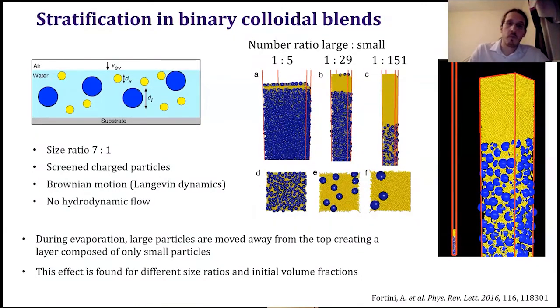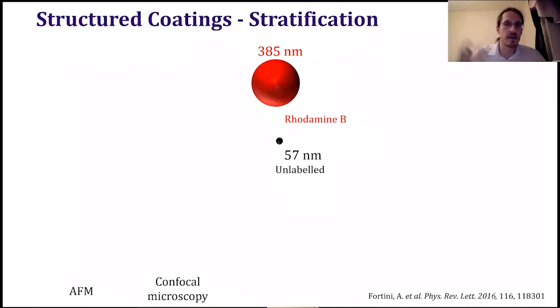So what I did here was check experimentally that this process happened. I blended particles, where the large particles have a red fluorescent dye, and the small particles don't have any dye, so they are unlabeled. And then I blended them together in different number ratios, and after drying the film, I looked using atomic force microscopy at the top and using confocal microscopy at the inside of the coating to see the distribution of the large particles, which have a red dye.